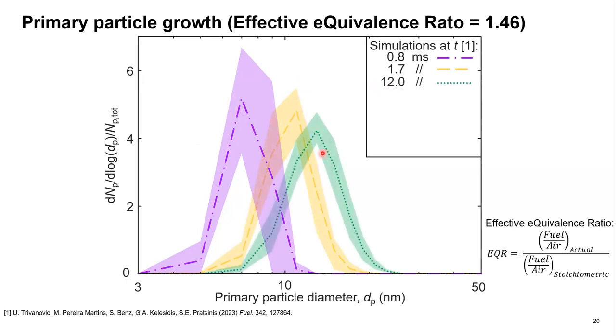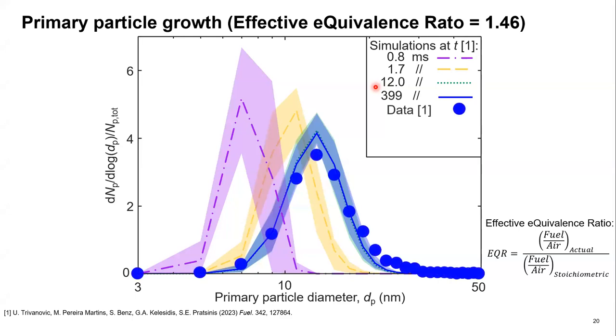And at 12, this increases to a median diameter of 14 nanometers. When we go out to the exit of the flame, which is corresponding to 399 milliseconds, we see that there's virtually no change between the size distribution observed at 12 milliseconds and that observed at about 400 milliseconds. So this really shows that after 12 milliseconds, the primary particle size does not significantly change anymore. And when we compare this to the experimental data that we collected, we see that the experimental data are in excellent agreement with the simulations at 399 and 12 milliseconds.